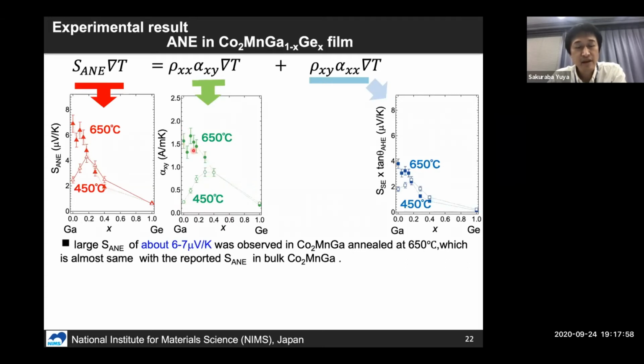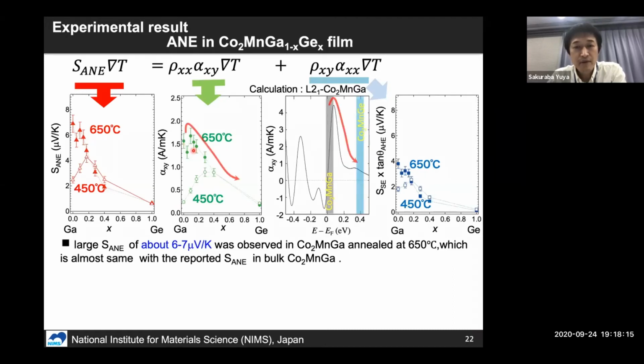So this result clearly suggests that for obtaining a high alpha XY, it is necessary to realize a high degree of L21 ordering. And if we compare this experimental tendency of alpha XY with the theoretical Fermi energy dependence of alpha XY, we can see qualitative agreement between the experimental alpha XY and the theoretical alpha XY.